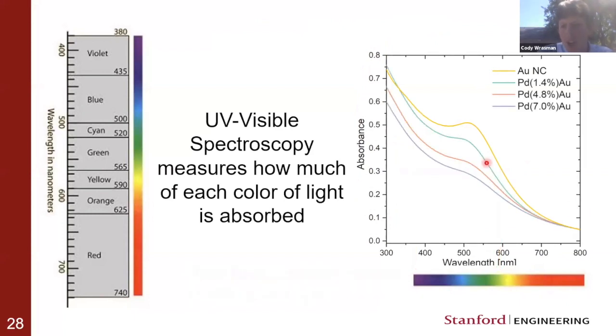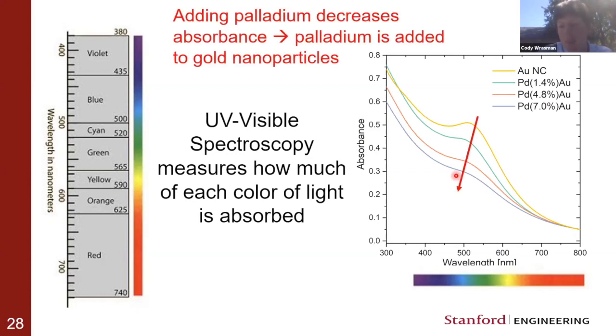If we look at how those nanoparticles compare as small amounts of palladium are being added, you see that the absorbance over in this area starts to go down. We use this as an indicator that the palladium is actually being added to these gold nanoparticles, that the properties of the nanoparticles are being changed. As a result, these nanoparticles no longer appear red. They appear closer to black.